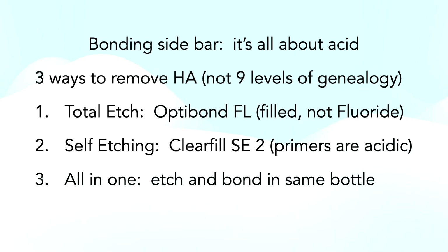Okay. Clearfil SE2 is, by peer review research, the gold standard. So there are other good ones out there, but that's the gold standard just because so much research has been devoted to it. Total etch, Optibond FL. FL stands for filled, not fluoride. Okay, they're the gold standard total etch. Now, if you're doing total etch, you're getting 3 to 5 micron denuded collagen fiber instead of 1 to 2. And so in terms of bond strengths, total etch still is the gold standard, but you approximate the results with SE, and it's a little more idiot-proof for reasons we're not going to go into yet.